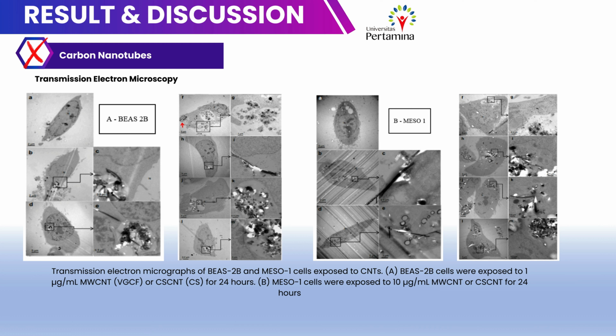Although MSTO-211H cells were exposed to MWCNTs and CSCNTs at tenfold higher concentration than BEAS-2B cells, CNT fibers and agglomerates were not specifically associated with lysosome and instead were distributed throughout the cytoplasm while being removed from the nucleus, with no obvious effect on adhesion or viability.